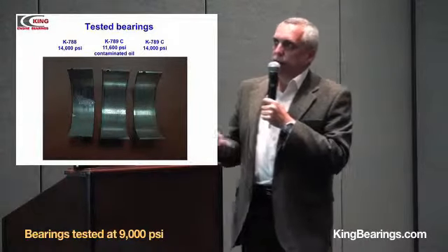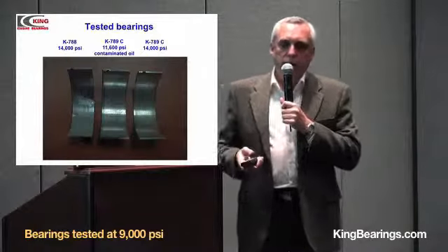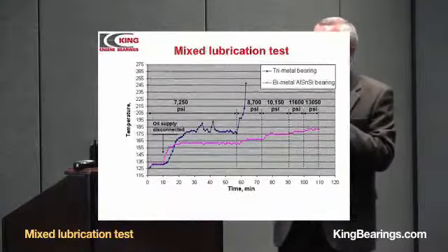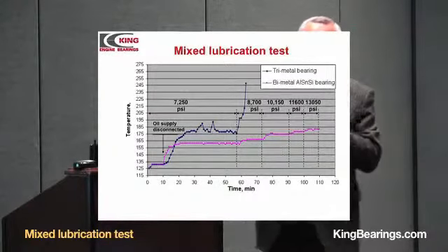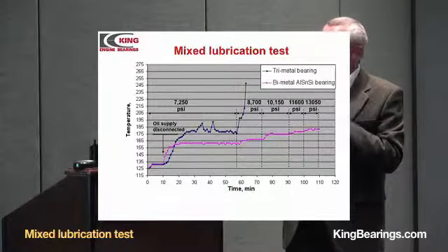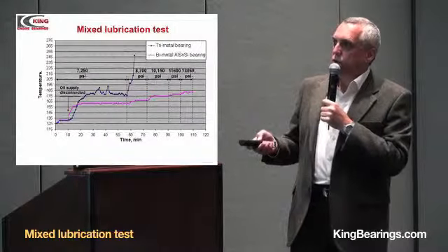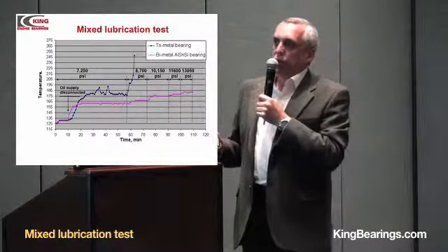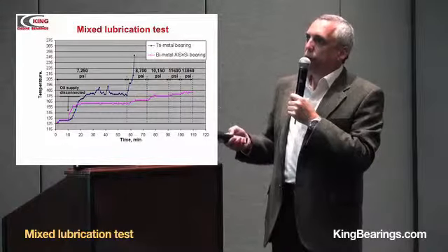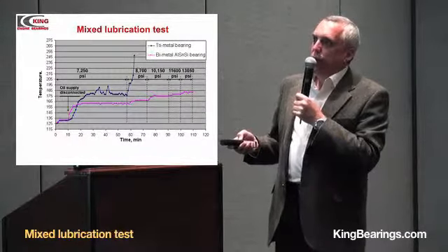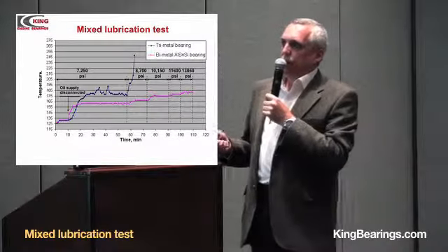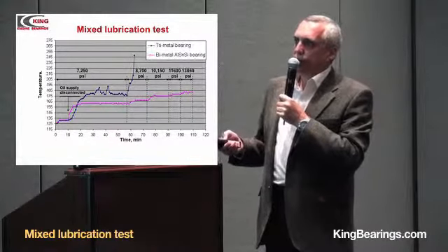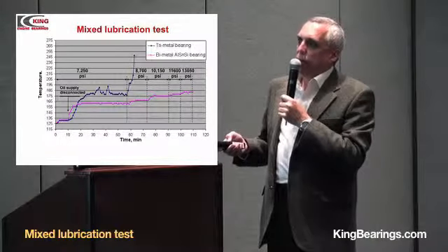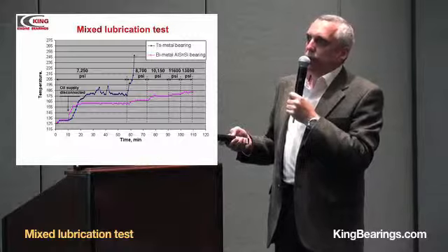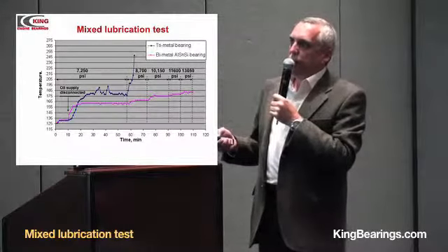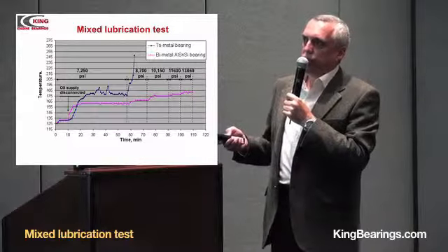This is a very interesting test, also made in this test rig. Two different materials were tested at mixed lubrication conditions. And you see here the temperature versus time, the temperature of the bearing back. For example, this material, this is trimetal material. When the oil was disconnected and the regime of mixed lubrication started at this point, the bearing back temperature increases. It stabilized at about 180 Fahrenheit with some peaks which indicate pre-seizure conditions.